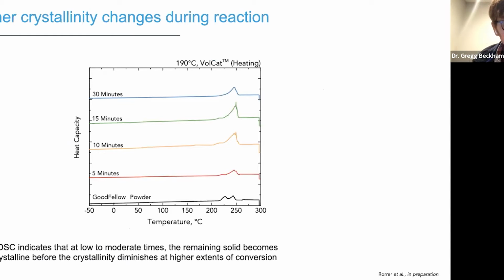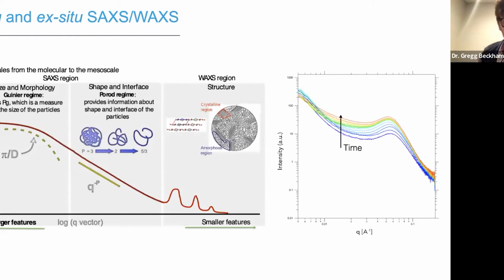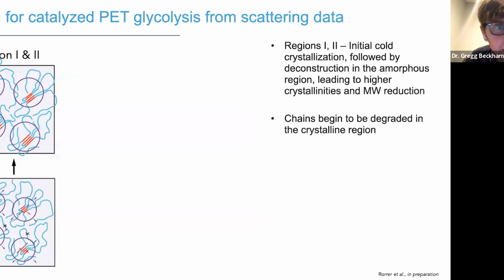And we also see concomitant polymer crystallinity changes during the reaction, going again from this powder substrate and now showing ex situ DSC traces. The remaining solid, as you would expect, becomes more crystalline before you get to high extents of conversion, when you start to see reduced crystallinity. And we've been working, as I mentioned earlier, with Chris Tassoni at SLAC at Stanford to do both in situ and ex situ small angle X-ray scattering, as well as wide angle X-ray scattering, such that we can collect larger features in the polymer physics behavior, as well as smaller features with small and wide angle X-ray scattering, respectively. And so this is what we've come up with so far as a mechanistic, cartoon-like model for PET catalyzed glycolysis from these scattering data.